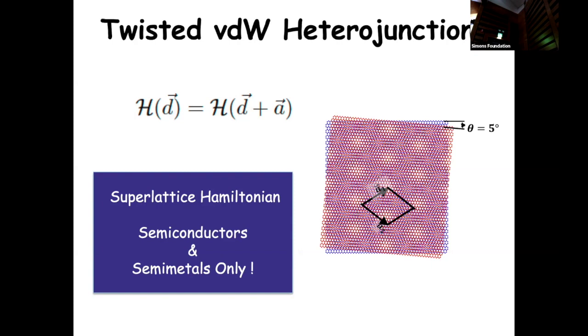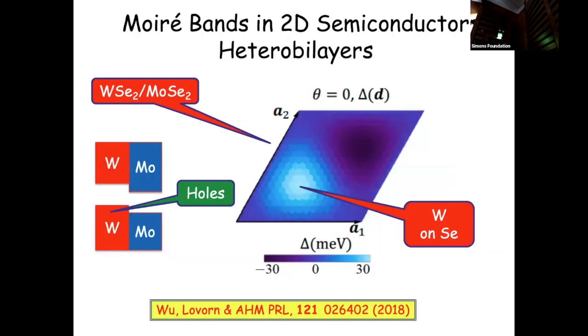And in this case, since there's only one state there, this is just a number that has to be periodic when I move one lattice relative to the other by a lattice constant. Of course, we can only get away with this kind of trick in semiconductors and semi-metals. But in the Moiré pattern, what happens then is that the pattern simply acts as a periodic scalar potential that has the periodicity of the Moiré pattern. So the system we can realize is a 2D electron gas with an approximately periodic sinusoidal potential.